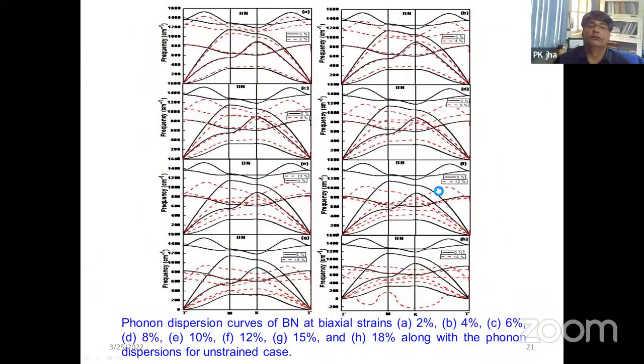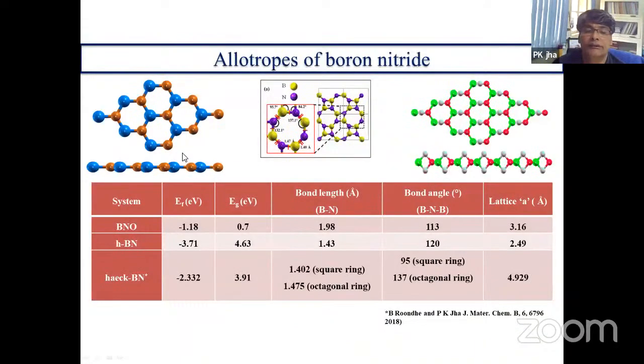And so is the phonon dispersion curve, right? So for the different strain percentages, that is for the 2 to 18% strain, you can see that the nature of the phonon dispersion curve is changing. Particularly, one thing you can focus on is the out of plane acoustic mode. And finally, you can see as you go on increasing the strain, this particular line, that is the out of plane acoustic mode, becomes linear, right? And this also gives some indication about the rippling in the graphene, right? Now, for different systems of boron nitride, you have different energy gaps, right? They are structural parameters, so we leave it.